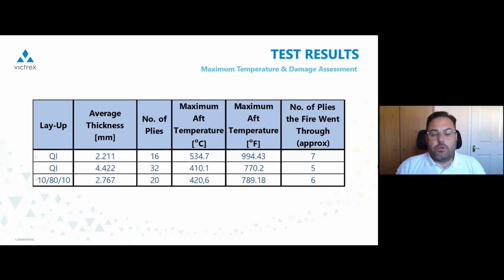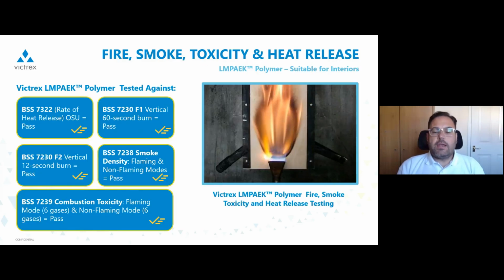Just to mention then, on the thicker panel, which was 32 plies, only 5 plies were damaged, which makes sense. The thicker the panel, the less damage you will have through. And then this is one of my last slides.